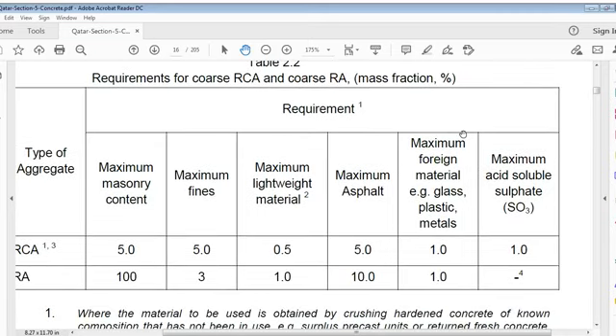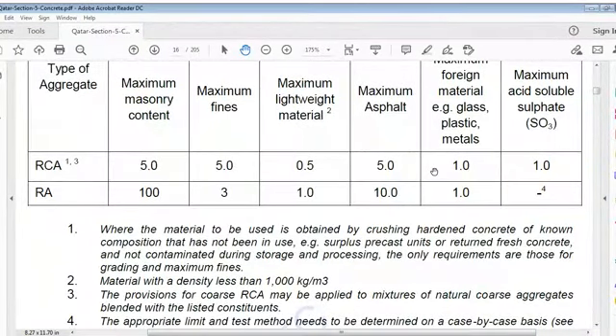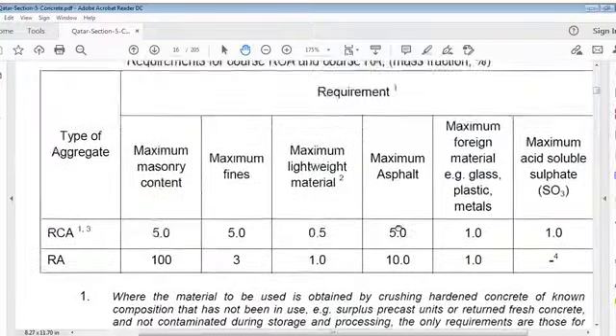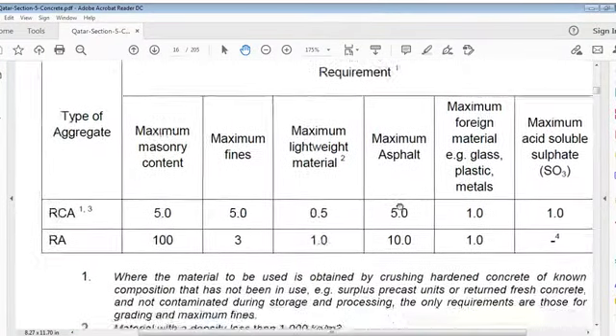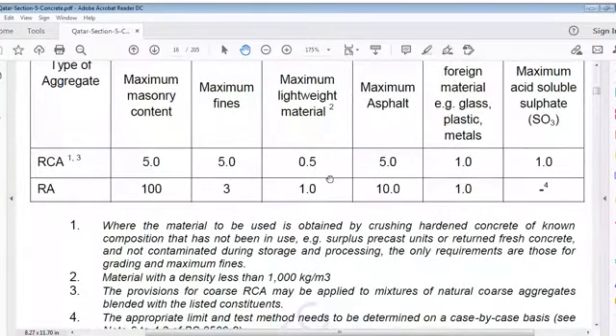Type of aggregate, maximum masonry content, maximum fines, maximum lightweight materials, maximum asphalt, maximum foreign material, namely glass, plastic, metals, maximum acid soluble sulfate SO3. RCA: maximum masonry content 5, right? That is the requirement, 5. Mass fraction is percentage. Maximum fines 5. Maximum lightweight material 0.5. Maximum asphalt 5. Foreign materials glass, plastic, metals 1. Maximum acid soluble sulfate SO3 1.